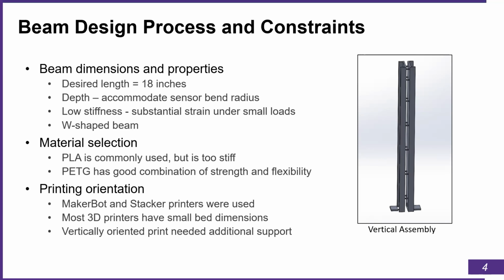With the material, we also wanted a low stiffness, we wanted the strain to be able to be seen clearly. So students looking at it, if it's too stiff, it's not going to show very much. And so we wanted the strain just to be substantial under these small loads. And then we also went with a W-shaped beam, also known as an I-beam, just because it's something that students are familiar with in these mechanics classes. They see it quite often. So we wanted it to be recognizable.